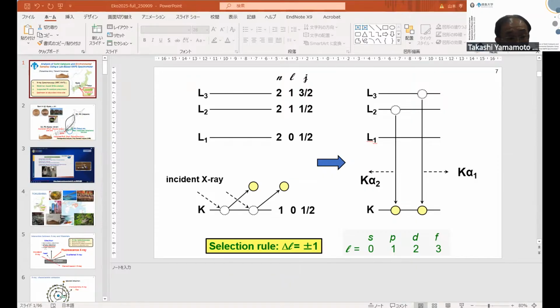Then a selection rule exists. Electron transition is strictly restricted, and this is delta L. Delta L is plus or minus 1. Then in the L1 shell, the 2s electron cannot transition to the 1s electron. The electron transition occurs between the K shell and the L2 and L3 shells. K alpha 1 and K alpha 2 characteristic X-rays occur.